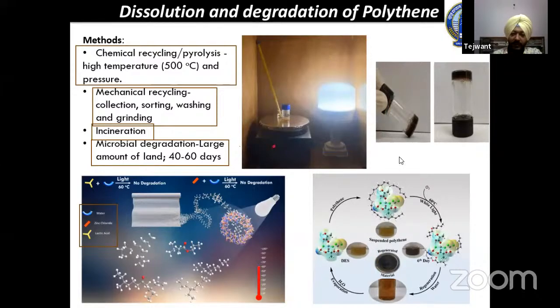So in this way, a very, very simple method has been established for the dissolution and degradation of polyethylene. And to be very frank with you, the method is new. It's a very unique method. However, the yield of dissolution was quite low. We could dissolve only up to 2 to 3%. So now we are trying to increase the yield of dissolution, and I'm hopeful it will take a bit of time, but certainly we will reach 10 to 15% dissolution of polyethylene where the solvent can be recycled.